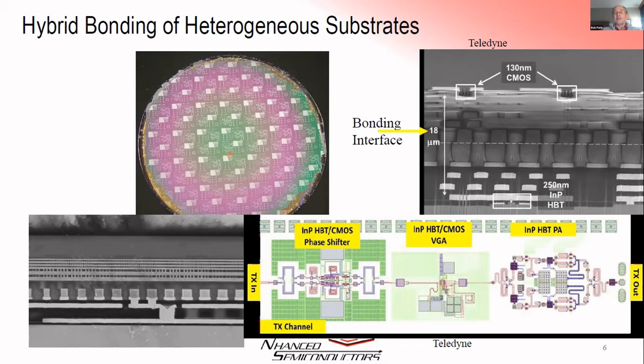So for things like infrared sensors, we can bond gallium antimonide to a CMOS ROIC, and often those CMOS ROICs are themselves composed of a couple layers of CMOS devices, and sometimes at different geometries. 130 nanometer analog interface for a ROIC is a nice node for a lot of technological reasons. And you can do data compression, you could do AI operations, but they often want to do that in something more like a 40 or 65 nanometer node, or even as far down, we've done some things as small as 12 nanometer FinFET technology in ROIC stacks.